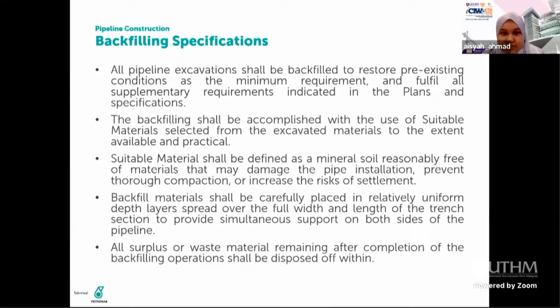The backfilling shall be accomplished using suitable materials, meaning that the materials we are using must not be harmful or damaging to our pipeline and the coating. It is defined as mineral soil reasonably free of materials that may damage the pipe installation, prevent thorough compaction and increase risk of settlement. So we need to carefully place the backfilling materials and ensure that it is a relatively uniform spread all over the pipeline, in order to provide simultaneous support on both sides of the pipeline. All surplus or waste material remaining after completion shall be disposed of as per usual construction methodology. Next, please.